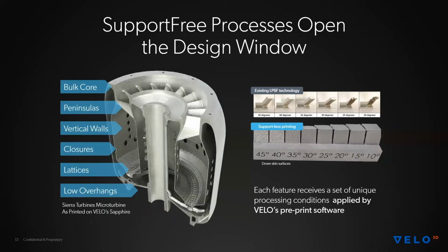On the right-hand side, you see an existing laser powder bed fusion system and how they struggle with low overhangs. The typical rule is 45 degrees before you see any breakdown or degradation in the process. Even at 40 degrees, you can see an increase in surface roughness, but then at 25 degrees and below, you have serious problems with resolving any type of geometric feature. Velo3D Sapphire just doesn't have this problem. We can go as low as 10 degrees, even lower in some cases, like I'll talk about in the next slides. But you see there's no degradation to the surface roughness, and it's very predictable, and it's an engineered surface. It's designed to be this way. And it's something that sets us apart from other incumbent metal AM systems.